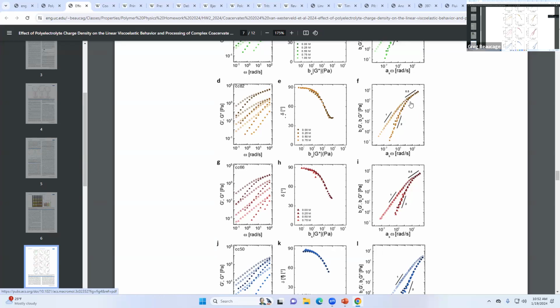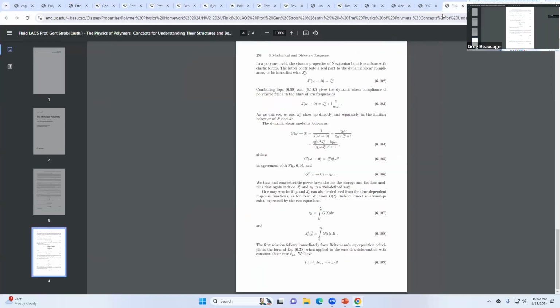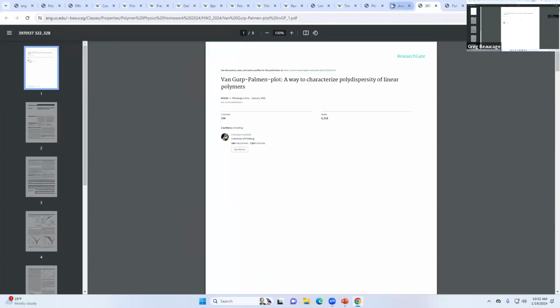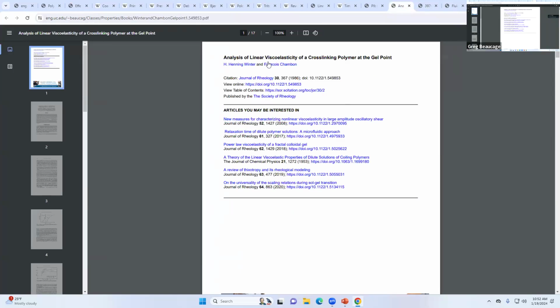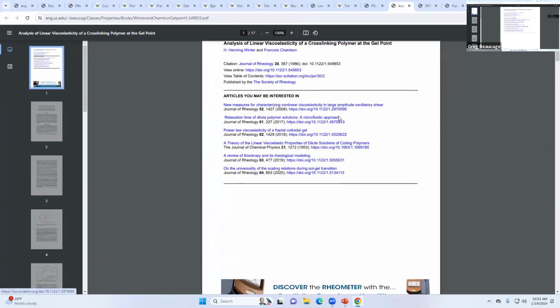That would be the normal behavior, but this behavior goes into this 0.5 thing, right? And there's two features here. One is the slope is 0.5, right? And the other is that the behavior of G prime and G double prime match each other there. So they have the same behavior. In fact, they have the same value. They both have this 0.5. So this is a thing from around the 1990s. Let's see, I have that paper here. This guy Winter figured out what that was, like why that happened. Henning, Winter, and Chambon. So it's called the Winter-Chambon theory.